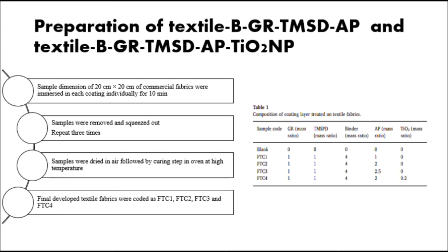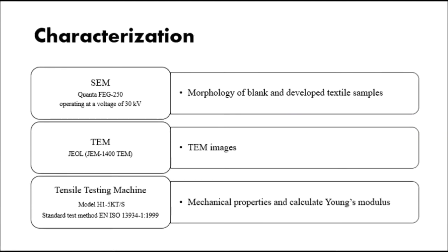And then the final developed textile fabrics were coded as the following, as shown in Table 1. For the characterization, we used a scanning electron microscope to study the morphology of blank and developed textile samples. TEM images were also taken, and the mechanical properties and the Young's modulus were calculated using a tensile testing machine.